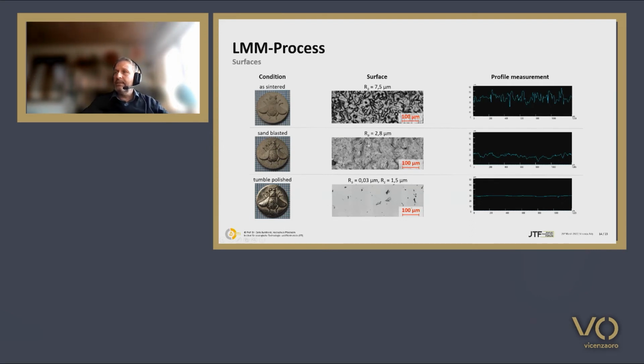If you sandblast the material, you can go down to 2.8 micrometers. And if you tumble polish, you can get Ra of 0.03 or Rz of 1.5. All the parts that I show now are not polished by hand. It's all done in machine processes. And again, as we don't have any support structures, the afterwork and the rework can be minimized very much.